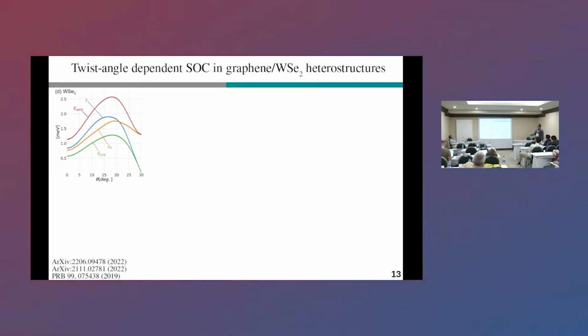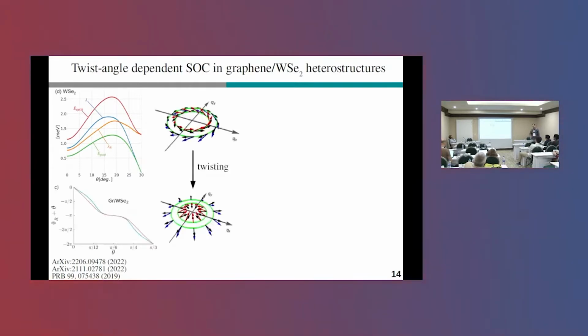The Rashba spin-orbit coupling does not show such a nice evolution. It stays more or less the same over the whole twist angle range. And on top of that, the Rashba spin-orbit field, this in-plane spin-orbit field, can be heavily deformed by twisting. It has been shown that at 0° twist angle, you have the typical tangential Rashba field you would expect. But once you twist to a certain angle, it can become purely radial.